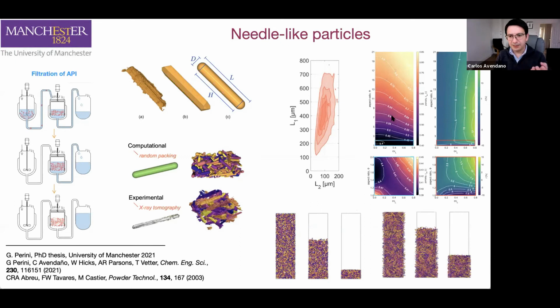It's maybe logical, but it's clear that the higher the aspect ratio is and the higher the polydispersity is, the higher the porosity should be. The interesting thing here is that we developed this technique to obtain those results in a matter of minutes, because these simulations are not in equilibrium. Basically, we are just sedimenting the particles under a very strong gravitational field. Essentially, they are not colloidal particles. They are mostly granular materials. But those simulations are extremely fast, and we can repeat them several times to get some statistical certainty on the accuracy of the results.